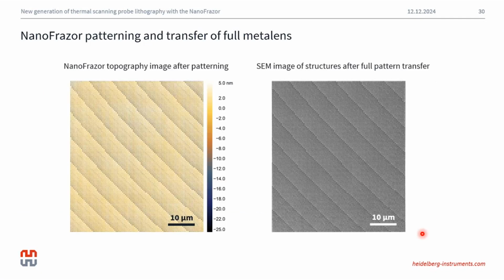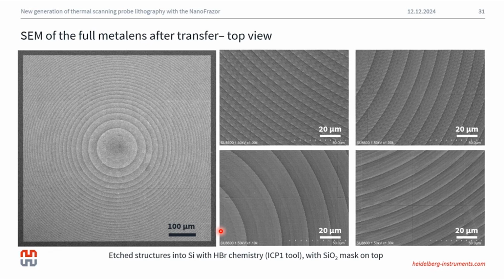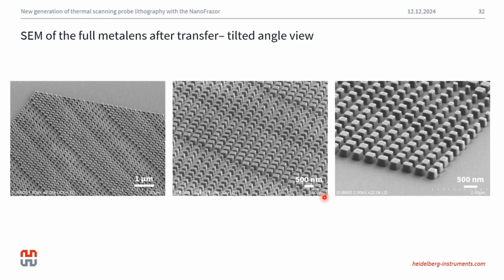If we look at snippets of the patterns, both as seen through the NanoFrazor system with this NanoFrazor generated topography image, and as seen through the SEM with the final generated silicon pillars, we see that these two images follow each other quite nicely. And we can also have a closer look at the finalized metalens etched into silicon and the different parts of this metalens. With this tilted view, you can also appreciate how the sidewalls of these individual elements are straight and smooth.